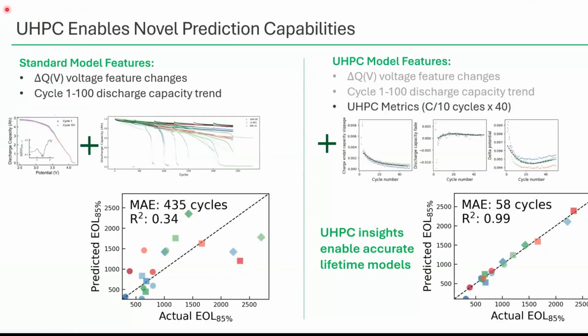In this work with Sandbox AQ, we were able to take standard model features, all published in works like the Severson paper on lifetime prediction, things like delta QV voltage curve changes between various cycles, and using discharge capacity trends early in cycling to try to predict what's going to happen later. Really, there's not a great correlation between predicted end of life and actual end of life.